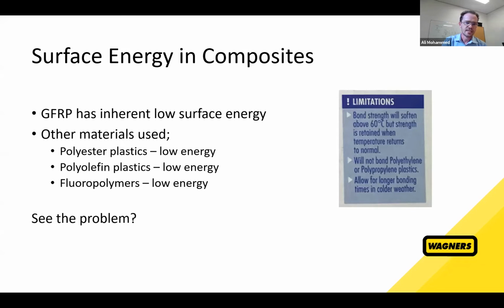When we look at GFRP composites in general, there are a few difficulties with looking for high surface energy for good wet out. The main one is that glass fiber composite has an inherent low surface energy, so it's difficult for an adhesive to wet the surface out. So just from the get-go, we need to look at options to increase our surface energy for better wetting out of the adhesive. We also use other materials here on site that are all very low surface energy materials, so polyester plastics, polyolefin plastics, and also fluoropolymer type materials. These are all low surface energy materials. So in general, we have a difficult time bonding here on site.